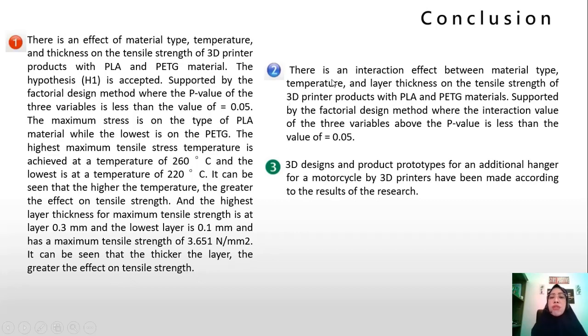Conclusion number 2. There is an interaction effect between material type, temperature, and layer thickness on the tensile strength of 3D printed products with PLA and PETG material, supported by the factorial design above, where the interaction p-value of the three variables is less than 0.05. And conclusion number 3, the 3D design and product prototype for an additional hanger for a motorcycle by 3D printer have been made according to the result of the research.